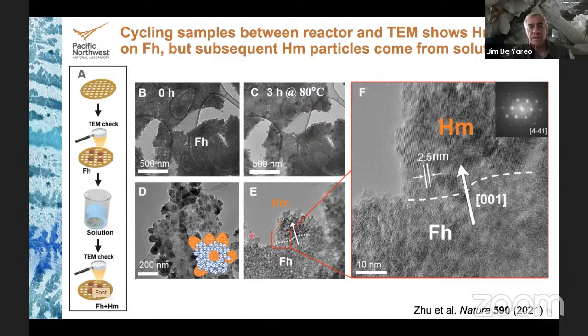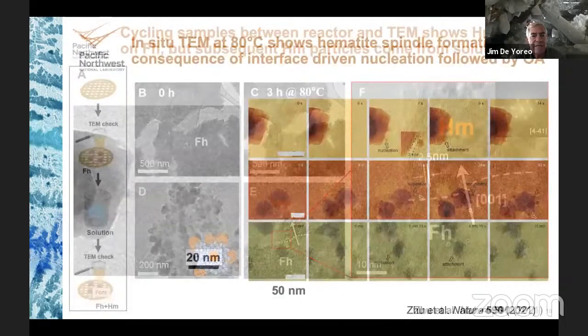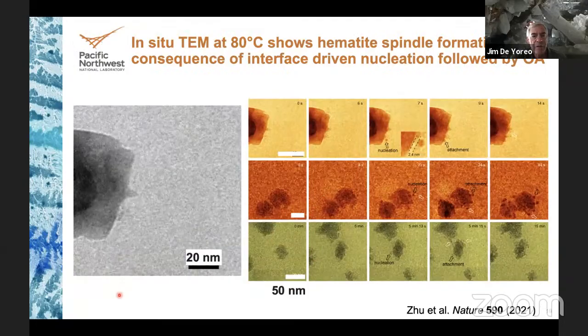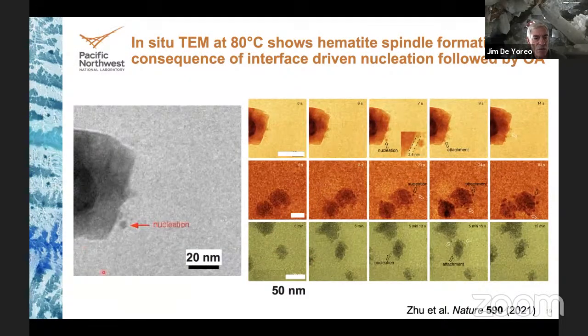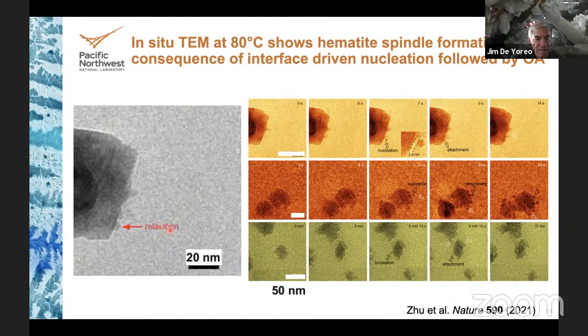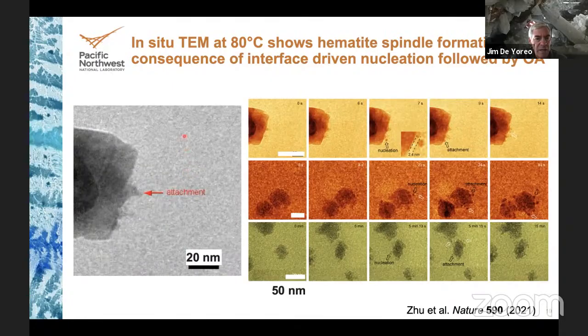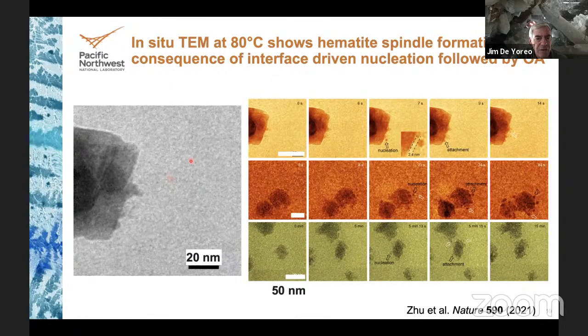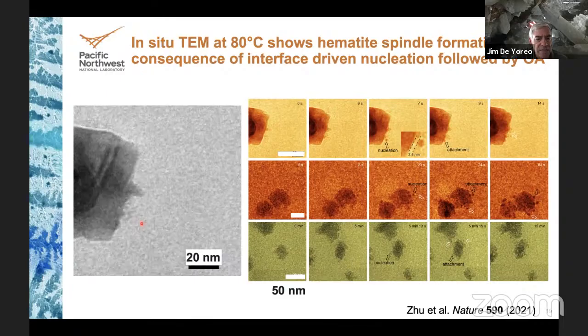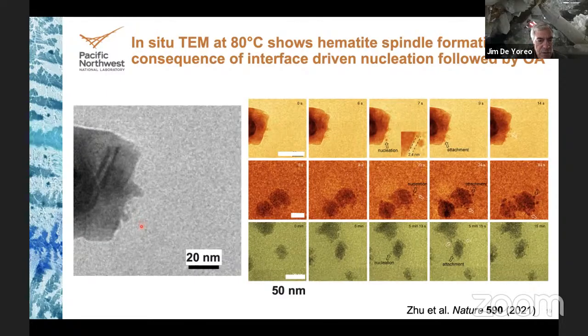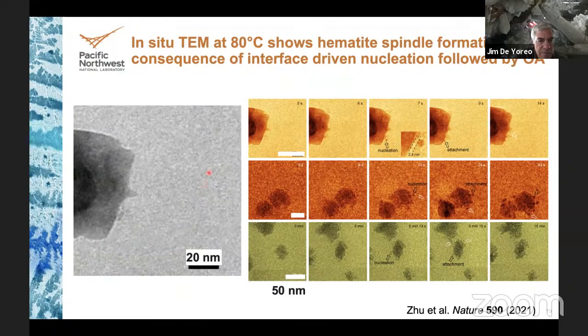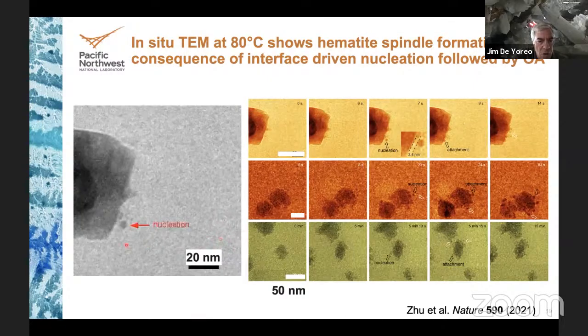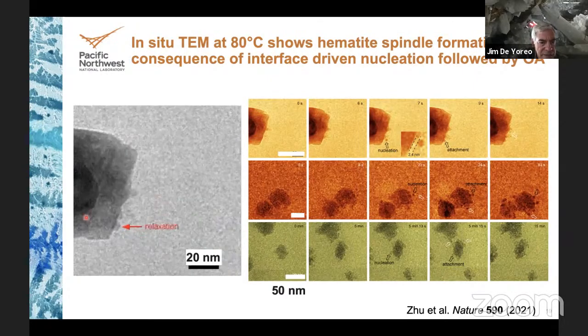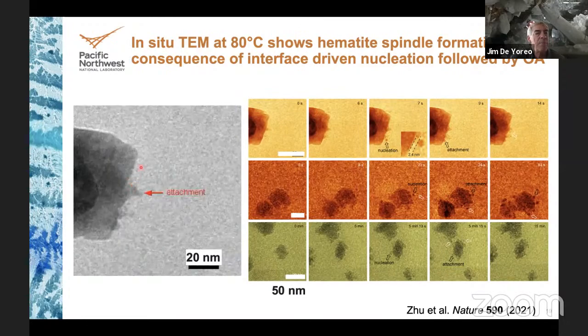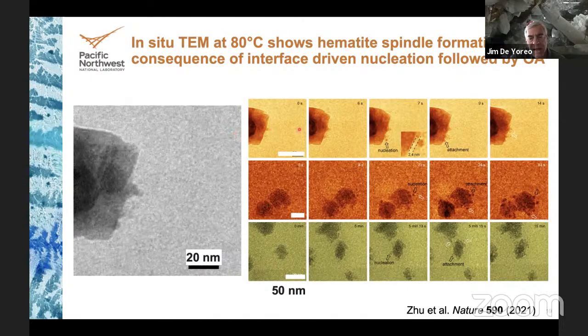And so in order to see exactly what was going on, we were able to do in situ TEM at temperature, at 80 degrees, using hematite seeds. And now you can see what happens. And what happens is, in the presence of sodium oxalate, the ferrihydrite dissolves away. It's just a source of ions. But new hematite particles form. They don't form out in bulk solution. They only form near the interface, and then they jump to the surface and become part of the particle.